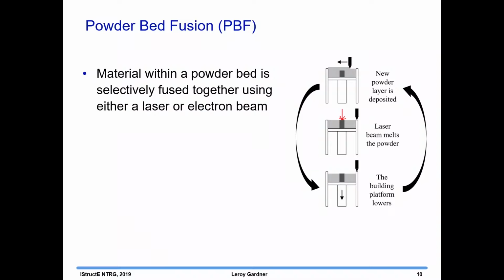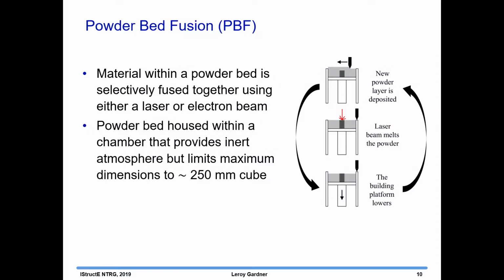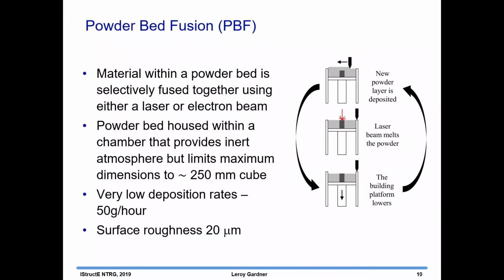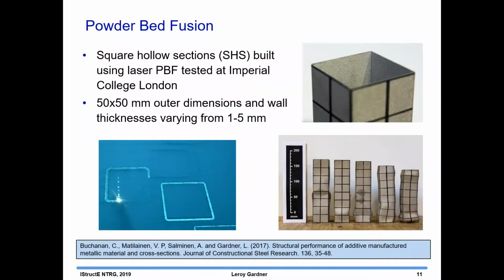For powder bed fusion, the input material is metal powder. It's selectively fused together using a laser or an electron beam. The powder has to be housed within a chamber, which creates an inert atmosphere, and that limits the maximum size of the components. It's quite a slow process, but it's very accurate, so it's suited for relatively small but quite intricate elements. We've done some initial testing on small structural sections produced by powder bed fusion. We've tested some square hollow sections of different local slendernesses and looked at their structural response.